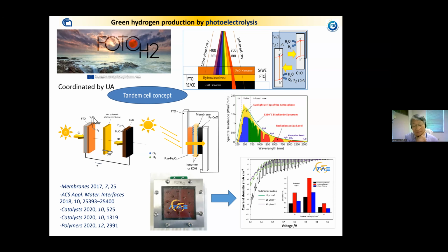That is the high energy gap semiconductor. So the wavelengths closer to infrared, which have lower energy but can pass the first semiconductor, should also pass the membrane. So the membrane should be transparent in that field. We have done a lot of spectrophotometric analysis of the membrane and selected one that is transparent in the useful wavelength range to reach the copper oxide.